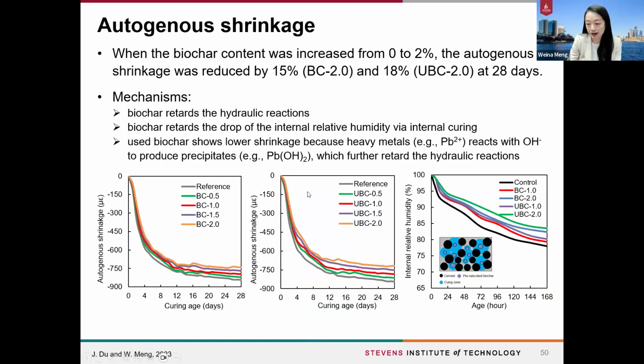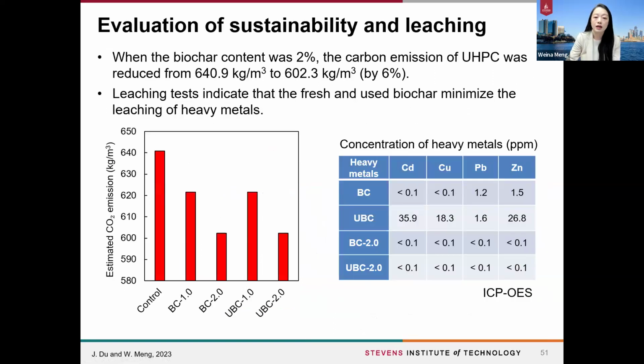And again, not surprisingly, as we use the biochar as the internal curing agent, we can more effectively cure the UHPC, so we can have the autogenous shrinkage significantly reduced. So even though for the biochar we didn't use a large amount, just very small, 2%, we can have a very, very high reduction in the CO2 emission, as the biochar itself is a carbon negative type of material. And also from the leaching test, we observed that the UHPC can lock the heavy metals permanently inside of it, especially for the used biochar cases. So this also demonstrates the environmental benefits of this study.